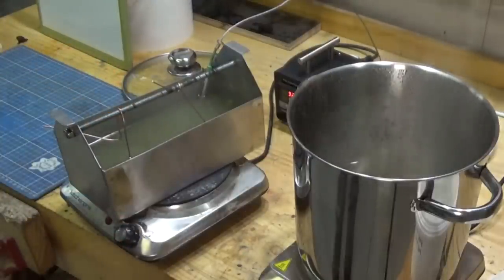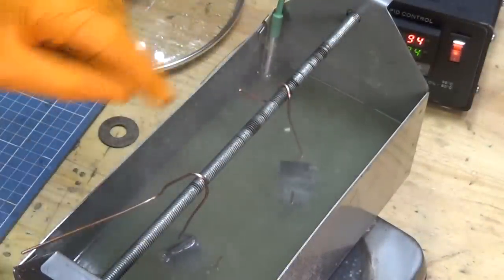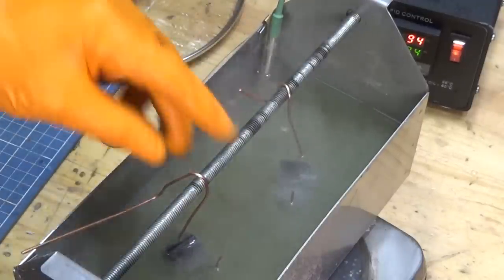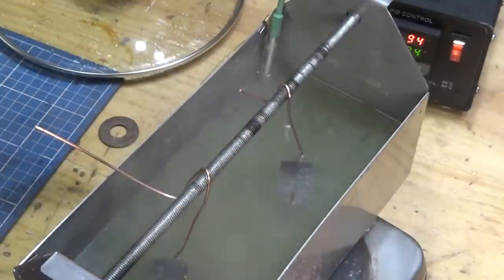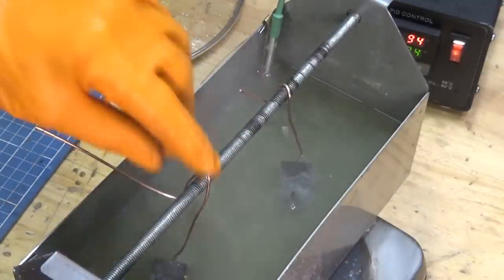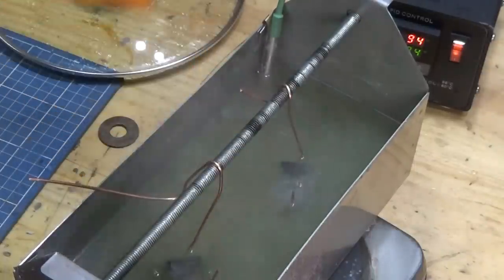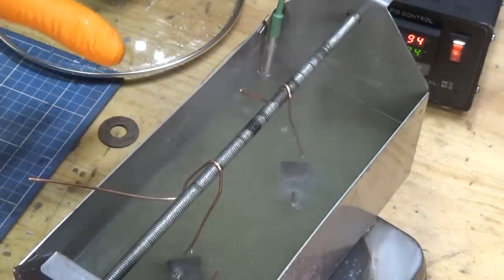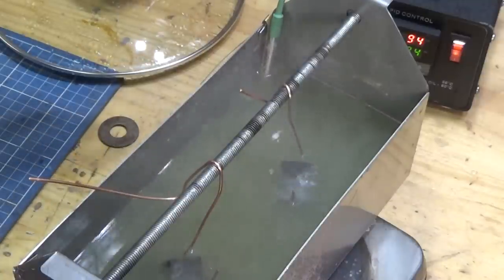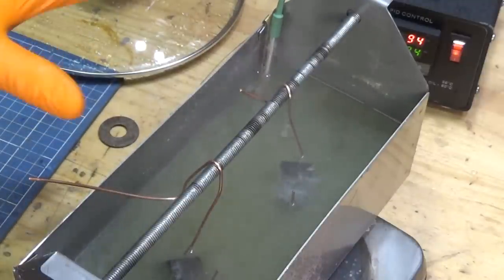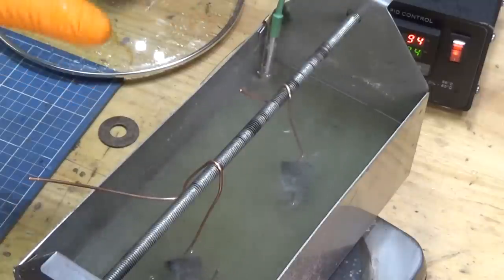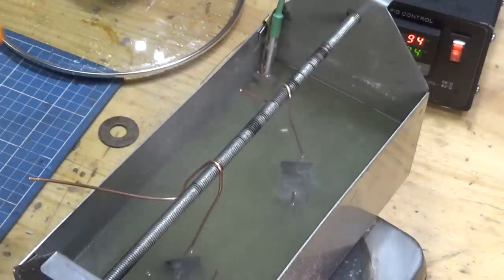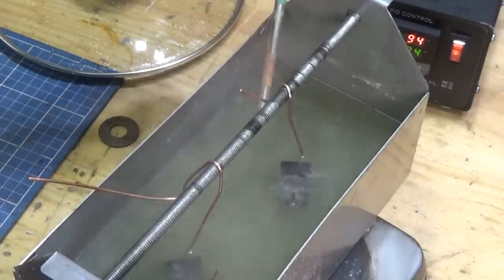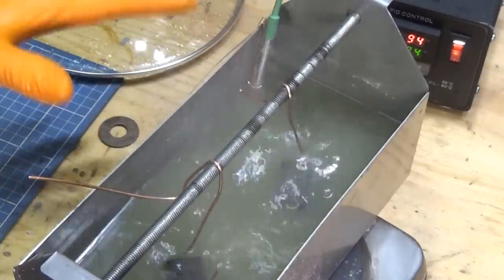Okay, let's have a closer look at that. You see those fizzing now, and that's an indication that the parkerising process is taking place. You'll also see the colour appear within a few minutes. It sort of goes a grey and then a darker charcoal grey when it's done. And I'm controlling the temperature of this in the tank using a PID controller. If you want to go back and look at my previous video, you'll see how that was made and the application of it for parkerising. But it's good, keeps the temperature monitored between 94 and 96 degrees, which is the recommended range. The little probe here is what we're using to sense the temperature, and that feeds back to the PID controller.